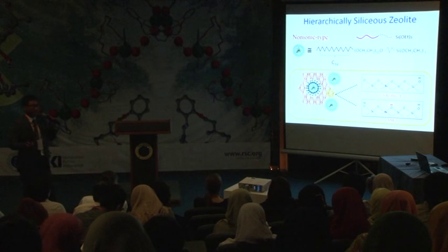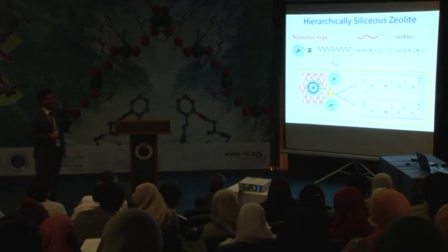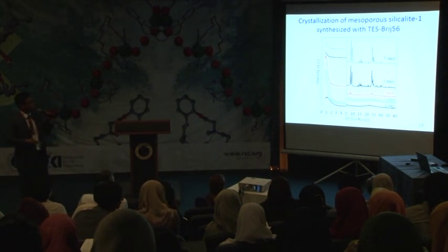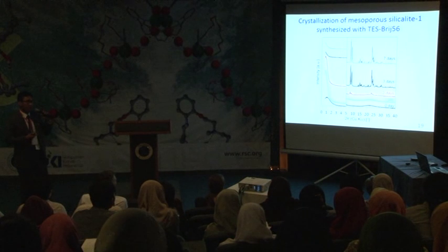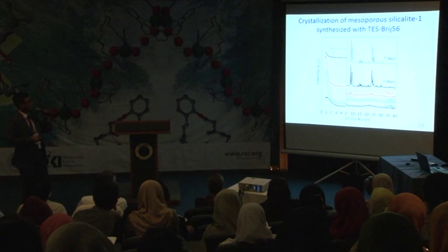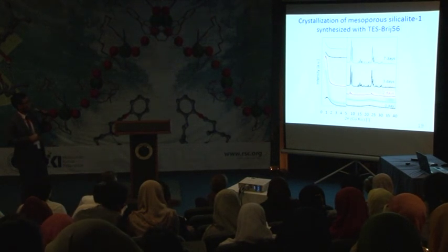If we use the cationic type of modified surfactants, probably it will not work because the electrostatic interaction will influence the nucleation. Because this is a neutral framework, we hypothesized that we should use the non-ionic type of modified surfactants. And you can see that we successfully synthesized this MFI zeolite, which is silicalite-1, the neutral siliceous framework. The high-angle XRD shows the typical pattern of MFI zeolite.